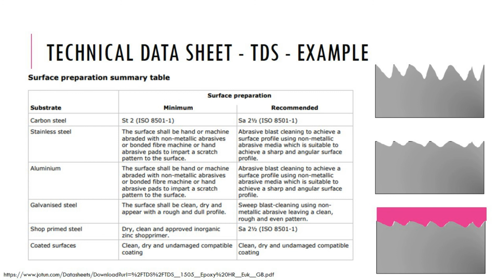If we use the blasting parameters given for carbon steel or stainless steel for galvanized steel, then there may be a chance of the loss of the galvanized layer, and this means that we will not only lose the extra protection that is there on that steel, but we will also be losing the adhesion between the upper coating and the galvanized layer.